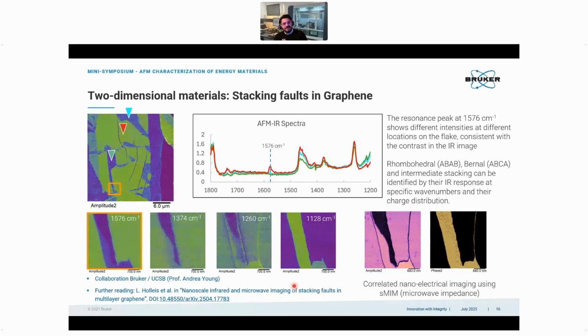So what this AFM-IR measurement allows in this case is, what you are looking at are maps of infrared absorption on different graphene layers. Here we see the contrast at different wave numbers depending on the stacking faults of the different graphene layers. So depending on the type of stacking, you see a change in the infrared absorption, right? And this correlates pretty well with electrical measurements. These measurements are done in microwave impedance microscopy, so they reflect changes in impedance, in the real and imaginary part, which basically reflect changes in capacitance and conductivity or resistance.